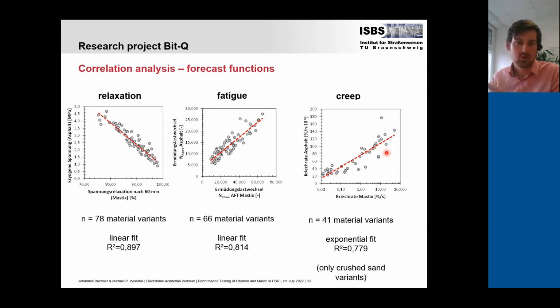Now, from all the results we gathered, we looked at forecast functions to actually forecast the behavior of the mixture from the mastic testing. I just copied them here. So you can see here for low temperature, we have 78 different material variants, because we also had some extended student thesis work, which were also included here. We have a linear fit around 0.9. We have here 66 different materials, linear fit 0.8. So it's not as good as for the low temperature behavior, since we have here some points which are quite far away from our linear regression, but still we can see a clear trend and correlation.